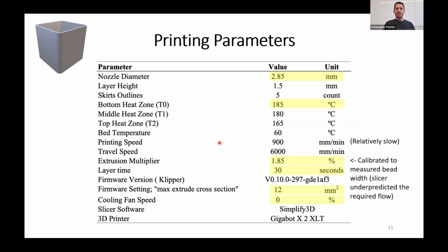This is the printing parameters that we have used. I'm just going to point out a few of these, but all of the details are in the paper as well. So we have used a 2.85 millimeter nozzle, and the heating that we have used is kind of towards the higher end from whatever is specified in the manuals for PLA for the Gigabot. And one thing we had to do was change the extrusion multiplier for our printing, because the slicer's expected bead width was specified as 3.4, and as we were printing, we found out it was much lower than that, so we had to compensate or calibrate using the extrusion multiplier. And once we did that, we achieved the expected bead width.